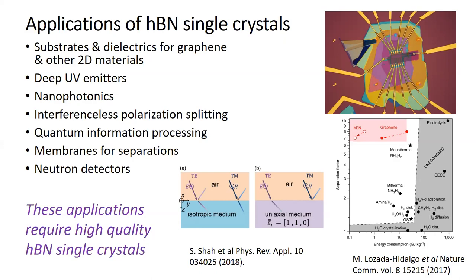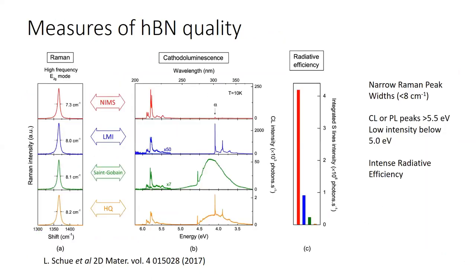So all these applications require high quality hexagonal boron nitride single crystals. And so how do we measure quality? I like this slide also from Shu. Basically, the common ways are to look at Raman spectroscopy, cathodoluminescence, and the radiative efficiency. They compared four different sources, but basically for the highest quality boron nitride, you should have a Raman peak width of eight wave numbers or less.